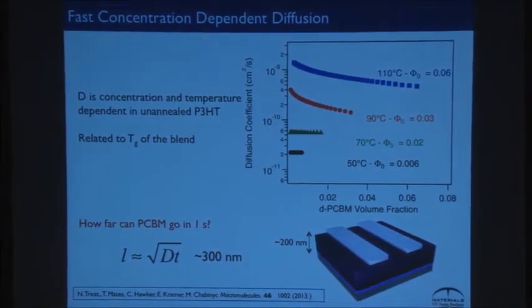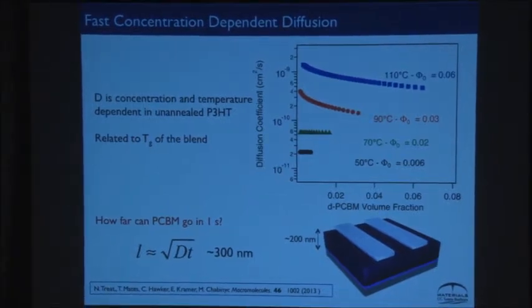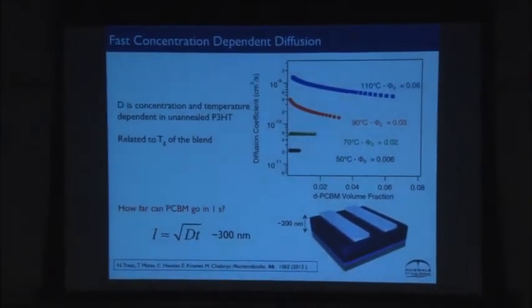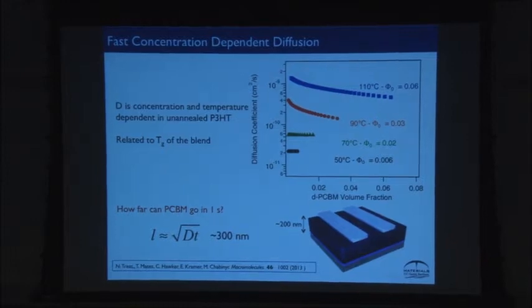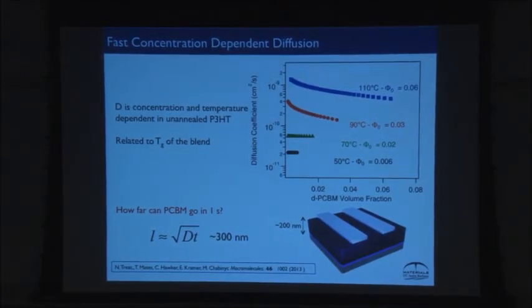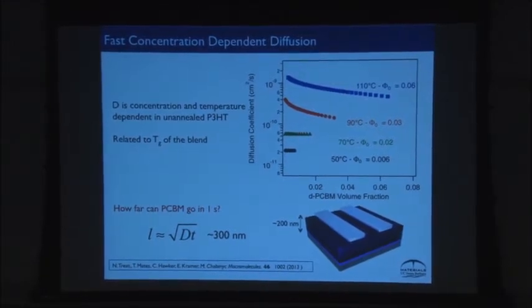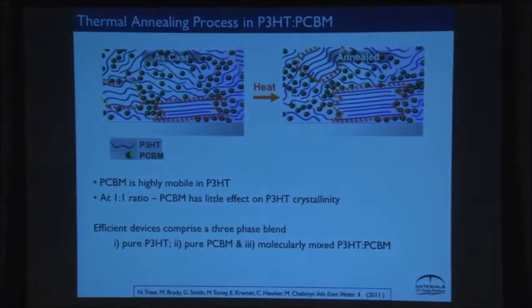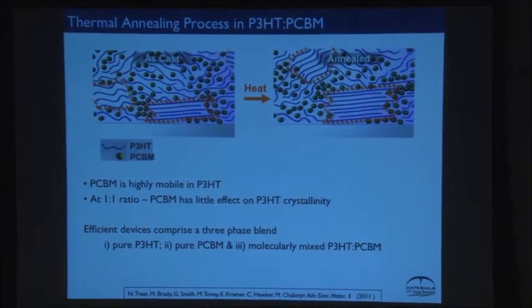Most people anneal these for like 5 minutes when they do these steps. So the fullerene is just moving around. It's basically insoluble, at least in these polymers. It's not the same in all polymers. In some of the other low gap polymers, you have to go to higher temperatures for this to happen. But you really have to imagine this glassy fullerene moving around at temperature, at will. And so what this says is that when we look at these cells, when we anneal them, what's actually happening is the polymer domains are crystallizing. The PCBM is moving around quite rapidly. But what it also forces you into is it says, well, there's going to be some pure domains of P3HT. That's the crystalline part. There's going to be some aggregated PCBM that you can see in TEM.